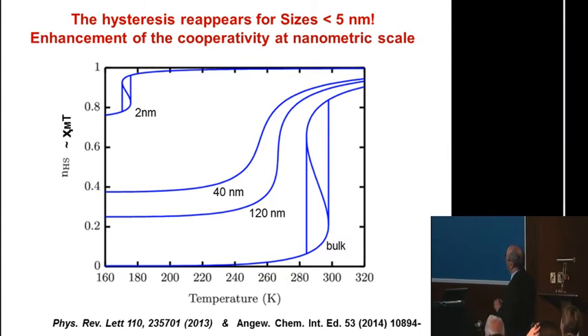So then what we have seen is that this is the bulk. You have a lot of interactions and then you can have a hysteresis loop. When you decrease to 120 nanometers, because you are cutting your elastic interactions, you can decrease your hysteresis loop completely. What is interesting here is that when you go further to very small particles, you see that you have a hysteresis loop appearing at very low dimensions. And for us, it was very surprising to have hysteresis at nearly a few molecules.